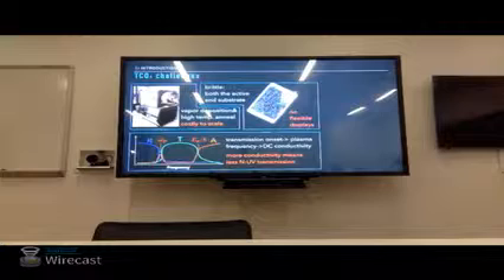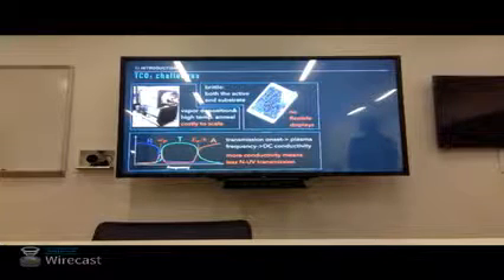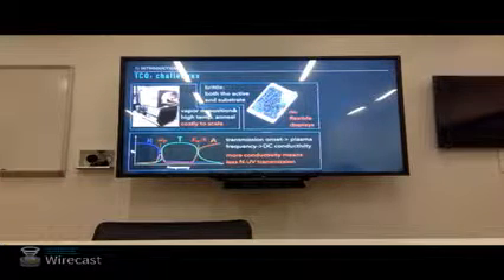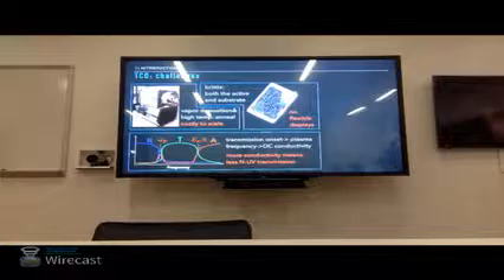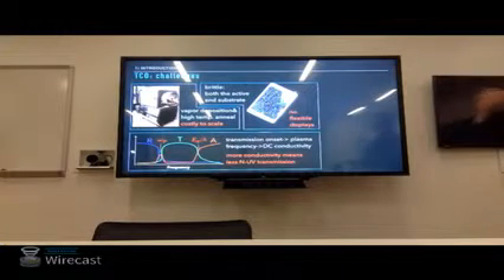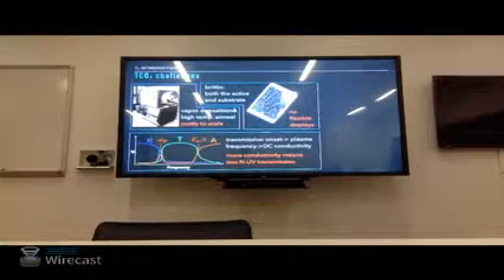Another drawback of TCOs, which is maybe a little less obvious, is that the optical transmission window is bounded by a plasma frequency, which is a collective oscillation of the free carriers, and a band gap. We're in a wide band gap semiconductor, so you push that plasma frequency to the red of the band gap. Now, if I want to make a more conductive wide band gap semiconductor, I can dope it even more heavily. What I'm doing is pushing that plasma frequency more towards the wavelengths that I start to cut off, and narrowing my transmission window. So we have a linked conductivity and transparency.